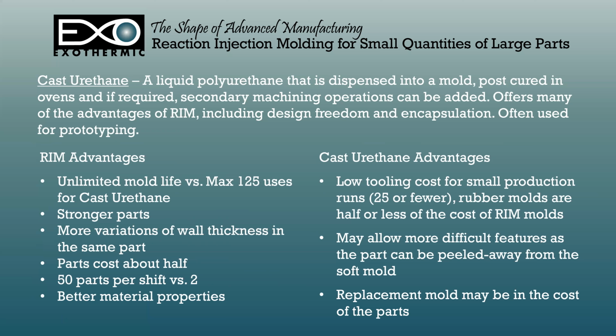with a large RIM part, you can do 50 parts per shift versus 2 parts per shift on a cast urethane part. And that's actually a very mechanical and difficult process that is a very manual process. And you get better material properties, particularly with our new Proxima material, which we'll talk about a little bit later on. But the material properties are better with the RIM parts than they are for cast urethane. So if you're looking for small quantities of large parts, then you want to look at RIM.